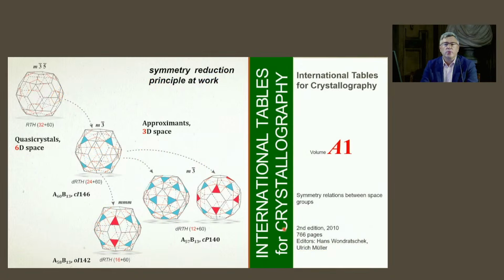I will try to fulfill this gap, and with this slide I wanted to show you some evolution of the rhombic triacontahedron, that is a common structure in 6-dimensional space of quasicrystals, by a very simple procedure of eliminating the vertices. So when doing so, we get some shell with less number of atoms, but we get some point symmetries that are now compatible with 3-dimensional periodic structures. For example, here we have 8 atoms less, here we have 16 atoms less, and so on.